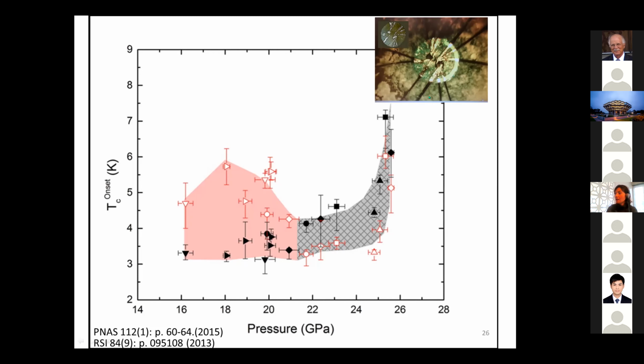And secondly, the kinetic effects. The thermal paths can be very, very different between different experiments, and we land in different parts of the phase space, which can make our experiments invalid. So what we have done is measure the samples in the same diamond cell next to each other. And what we've seen was quite remarkable.